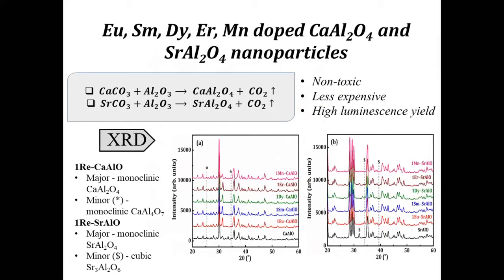We have prepared some of the aluminate samples, molybdates and tungstates. They are thermally not stable above 1200 degrees Celsius. And tungstates and molybdates are also more expensive. So we prepare the aluminates, calcium aluminate, which is also a material used in cement, and strontium aluminate. The starting materials are calcium carbonate and aluminum oxide. And you sinter it to a temperature of about 1400 degrees Celsius.